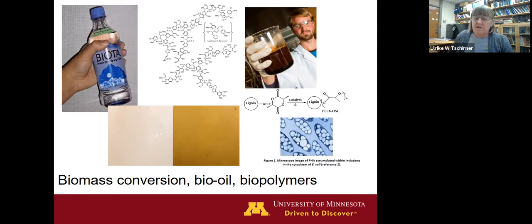There are other polymers on there, and I just recently had a project with an undergraduate student working on this. If you look at that blue picture with these little beads in there, these beads are made by bacteria. So this is a microbial process. We feed the bacteria sugar, they eat the sugar and they make the plastic. So there's no chemistry involved. This is 100% biology. At the end, you can see they look a little bit like stuffed sausages. Instead of a chemical process, you use a solvent to take out the polymer, and you reprecipitate it and you have that particular polymer. Some of these polymers are on the market, but they're still pretty rare and fairly expensive to make. So there is a lot of development that still needs to be done with this material.